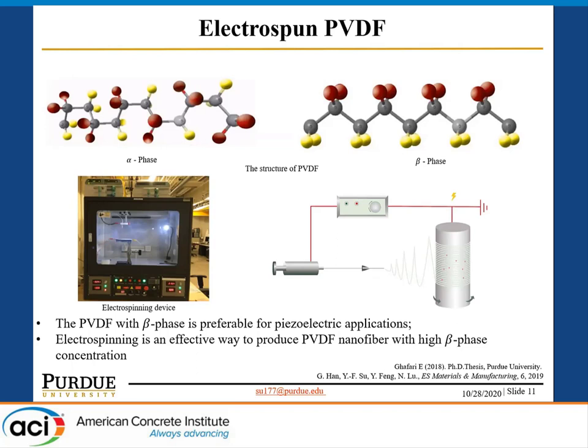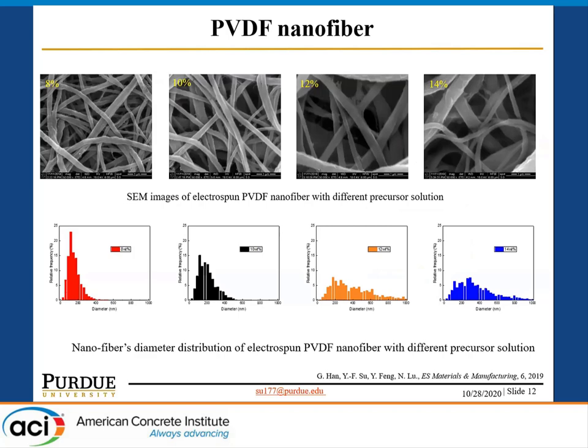For PVDF, the beta phase is more preferable for increasing the piezoelectric property, so we tend to increase the beta phase concentration as much as possible. And for the PVDF nanofibers, this is one of my colleagues. We work together. We have different concentrations of the PVDF precursor from 8% to 14%. And we found that for the 8%, we can have finer fiber, which results in higher poling by the electrospinning process. Therefore, the PVDF nanofiber with finer size has high beta phase concentration, which means we'll have higher energy harvesting efficiency.